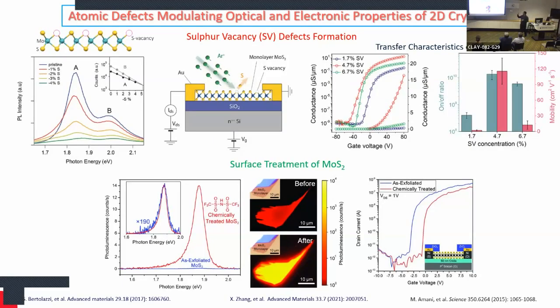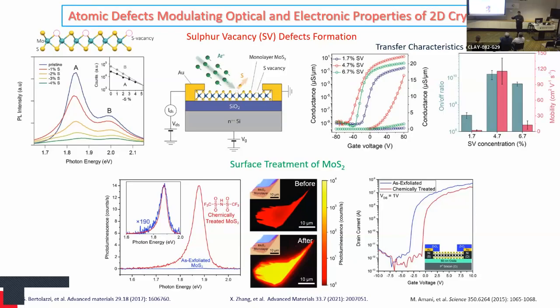For example, in this case, we have MoS2, which is a semiconducting 2D material. In that one, if you create some vacancies in the MoS2, for example sulfur vacancies, it can change optical properties. You can see in the top left corner, we have photoluminescence that will change, and also electronic properties change once you have more vacancies in the MoS2 on the surface. You can see there some sulfur is removed from the layer. It will change the connectivity and also the properties. And you can also retain these properties again if you do some surface treatment.